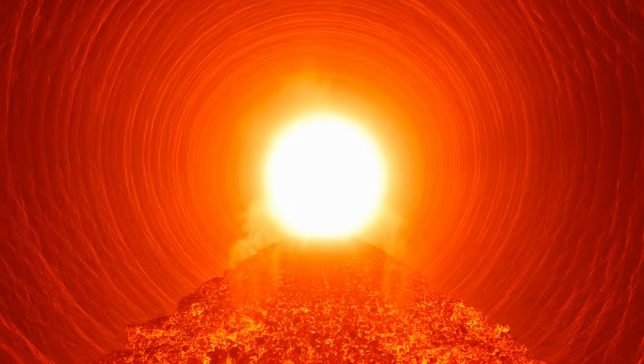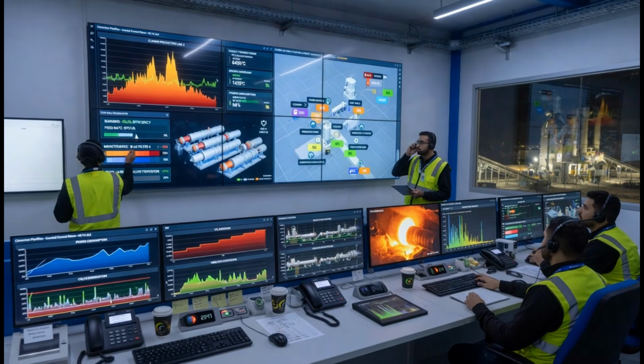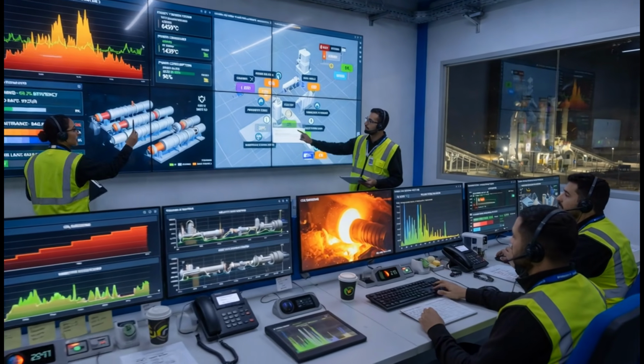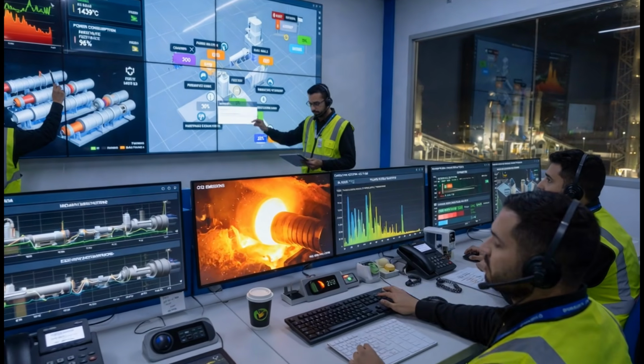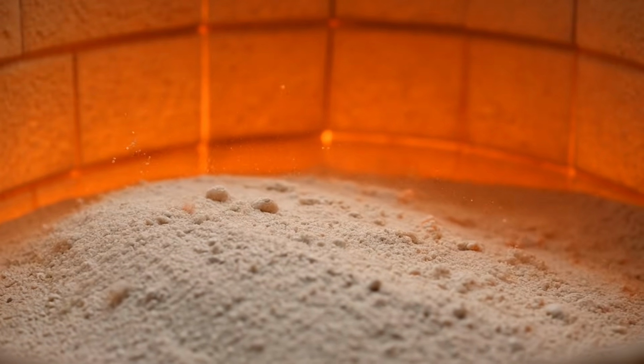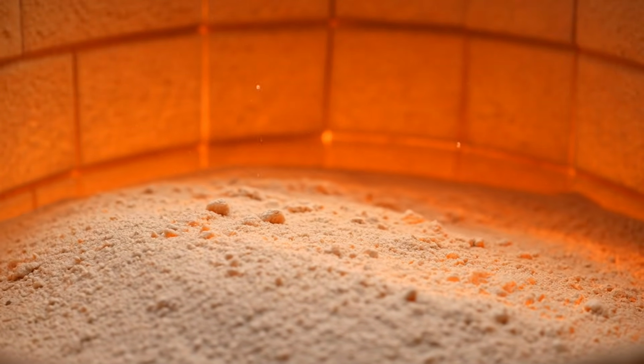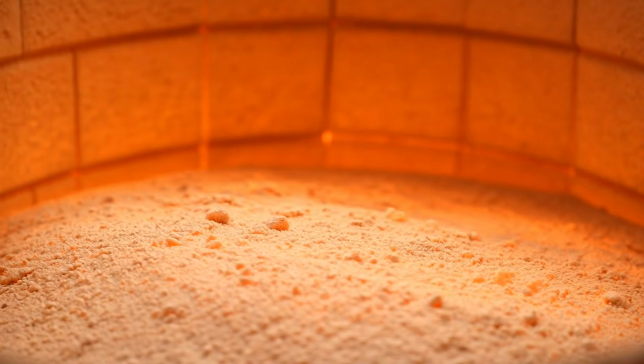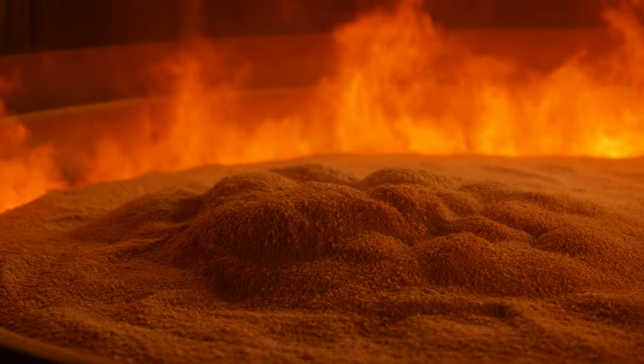Lava from a volcano is around 1,000 degrees. This kiln is hotter than that. At 900 degrees, the limestone breaks apart, releasing CO2. This is called calcination, and it's irreversible. At 1,450 degrees, the minerals partially melt. For a moment, this powder is liquid rock.